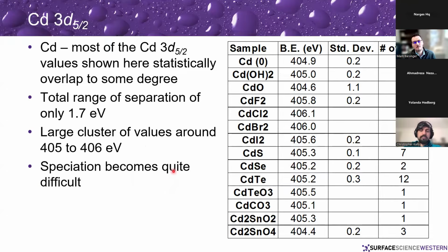If we look at peaks for the cadmium 3d 5/2 peak, you can see we have a whole list of binding energies here. But there's actually not a lot of separation of these binding energies. So the total range of separation from everything from the metal on through the different species is only 1.7 eV. And we have a large cluster of values around 405 to 406 eV. And so being able to say, okay, what species do I have just from a specific binding energy becomes very difficult. There's just too much error in there to get really good speciation from just the core photoelectron peak.